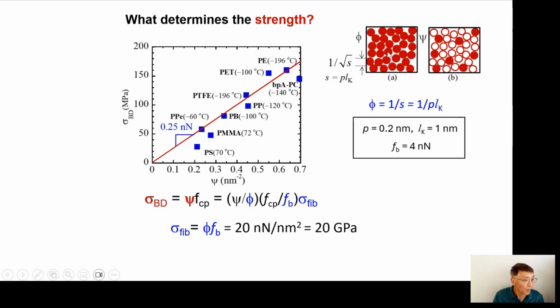But generally, your polymer, the ones we see every day, is still in a coil form. They're not in the fiber limit, which means this chain folds back and forth many times, wasting that cross-sectional area without bearing load. They only bear load once. So through that concept, you can understand that basically, what we see is a strength that's 2 orders of magnitude lower than the fiber limit. Due to what? Due to these two factors.